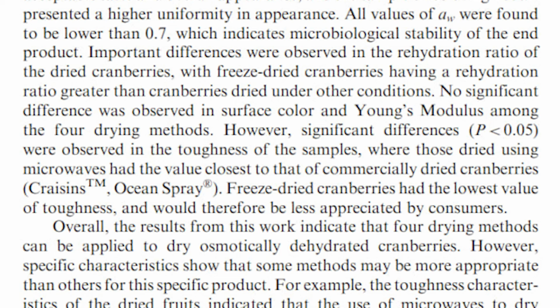Important differences were observed in the rehydration ratio of the dried cranberries, with freeze-dried cranberries having a rehydration ratio greater than cranberries dried under other conditions. No significant difference was observed in surface color and Young's modulus among the 4 drying methods. However, significant differences were observed in the toughness of the samples, where those dried using microwaves had the value closest to that of commercially dried cranberries, Craisins, trademark Ocean Spray. Freeze-dried cranberries had the lowest value of toughness and would therefore be less appreciated by consumers.